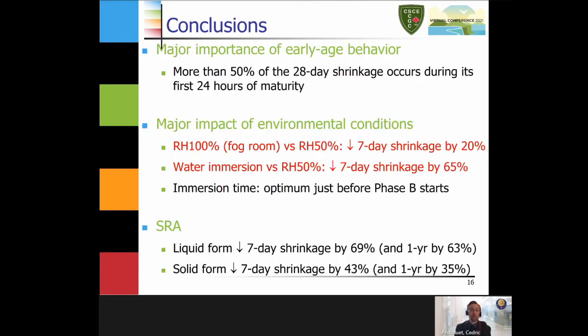So what are the conclusions we can draw from this experimental program? First, we've demonstrated that there is a major importance of the early age behavior, as more than 50% of the 28-day shrinkage occurs during the first 24 hours of maturity. That is significant. Another interesting conclusion is the major impact of the environmental conditions. We've seen that we can reduce the shrinkage by about 20% when the concrete is at a relative humidity of 100%, meaning in a fog room. But we've seen that immersing the specimen in water provides a reduction of shrinkage up to 65%, which is really much more efficient than just having a relative humidity of 100%. And finally, the immersion time is optimum just before phase B starts.